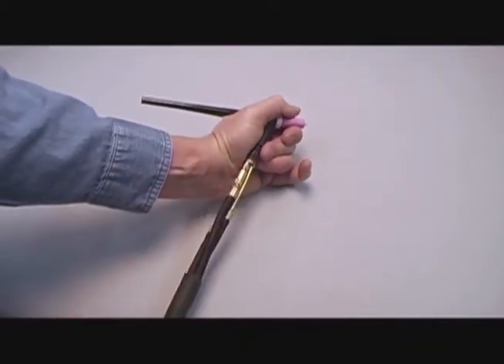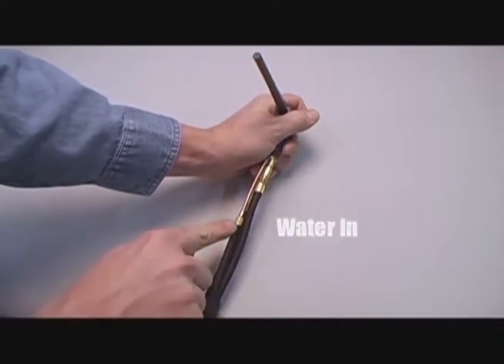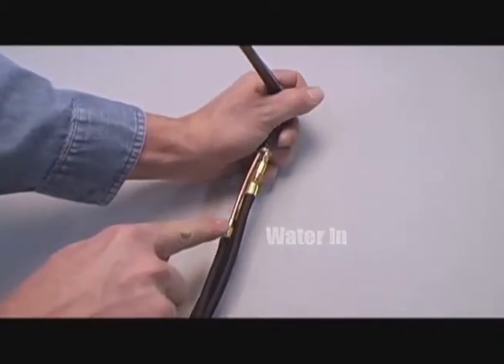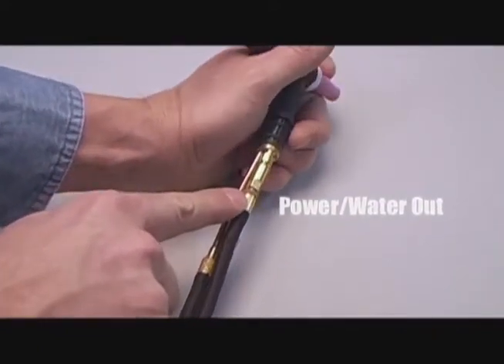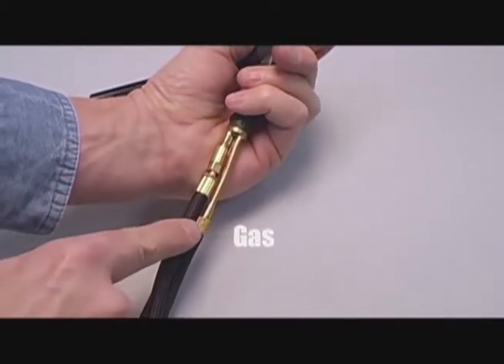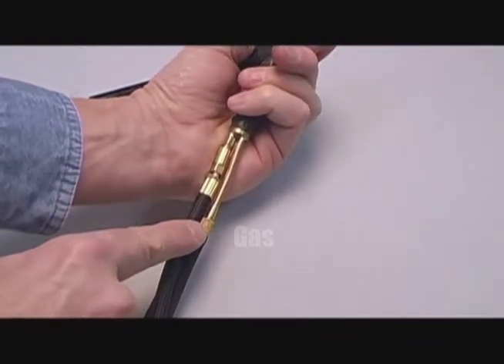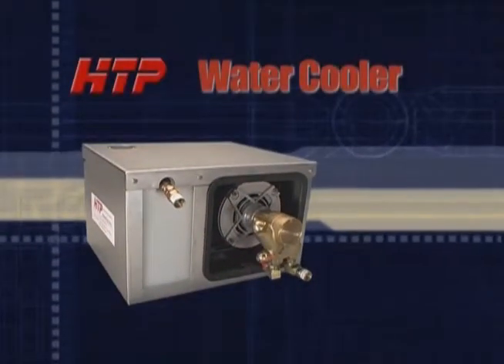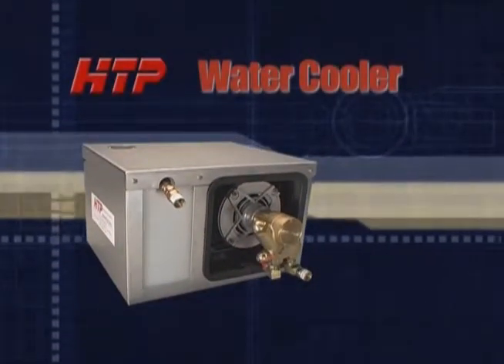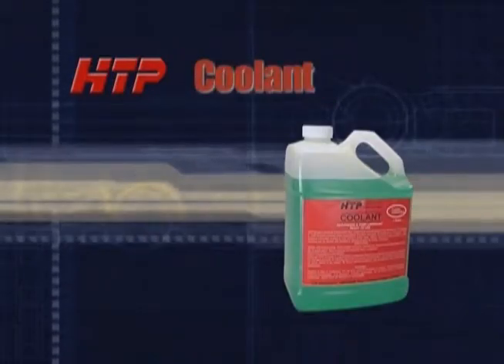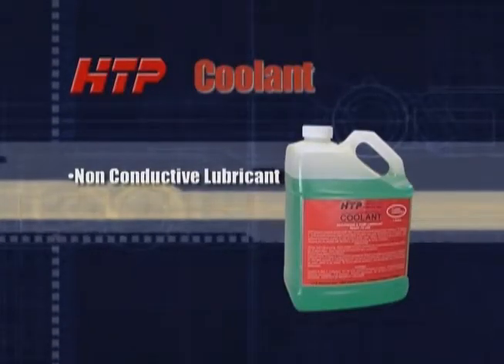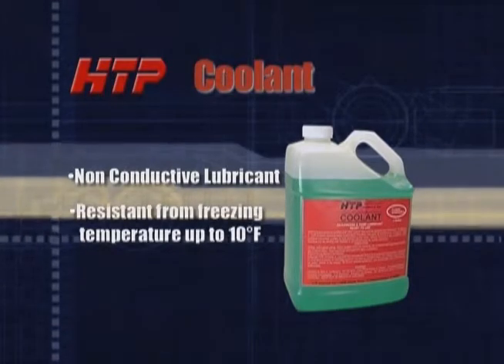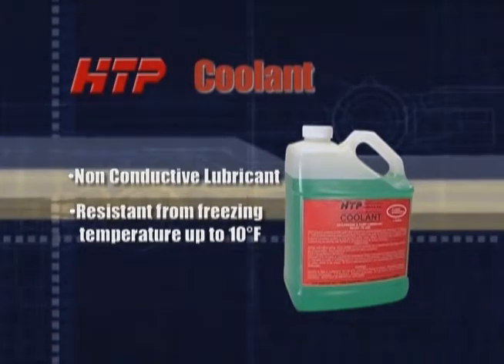A water-cooled torch has 3 cables: water in, power, water out, and gas. Water-cooled torches are generally connected to a water cooler, which provides a source of cool water for the torch. And the coolant is a non-conductive pump lubricant that also provides protection from freezing to 10 degrees Fahrenheit, such as the HTP coolant.